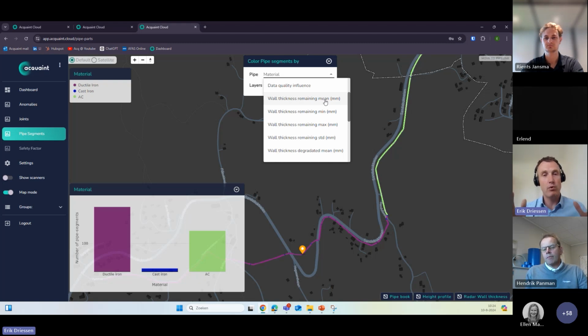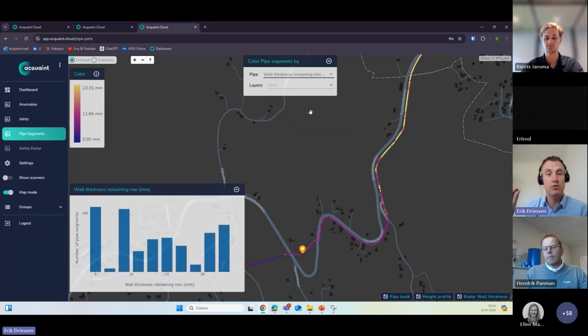What is the minimum wall thickness that we spotted? What is the maximum wall thickness? And what is the average wall thickness? So that applies per pipe segment. And of course, as a pipeline owner, you're typically interested in the extreme. So that's why we select the minimum wall thickness. So again, per pipe segment, what is the thinnest part of the pipe that we have observed? And because we have asbestos cement and ductile iron in the same view, you get quite a big spread, and that is hard to compare.